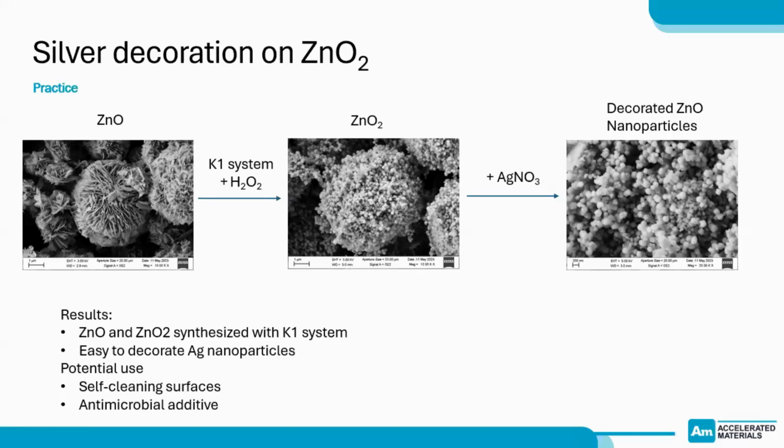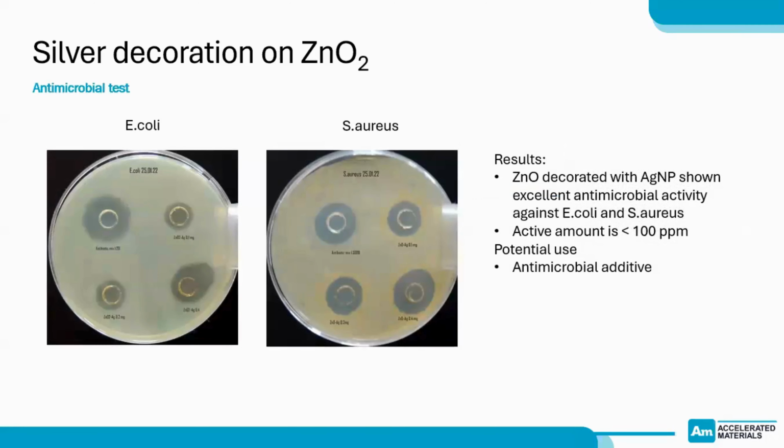And over here you can see that it exhibits a very good antimicrobial activity, indicated by the clear circles for E. coli and Staphylococcus aureus. And the active amount is very small, can be below 100 ppm, when you add it into different matrices.